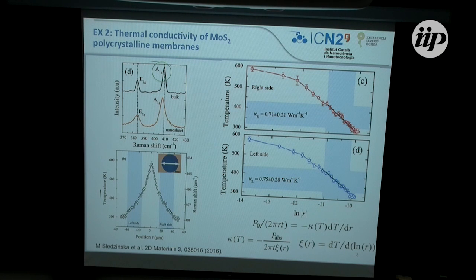So the second example has to do with what our chairman talked on Monday, which is thermal conductivity in molybdenum disulfide. So we obtained polycrystalline molybdenum disulfide, exfoliated and put it on an electron microscope grid, and proceeded with our experiment. Here we use the technique that Joni Ahopelto explained to you on Monday, basically laser Raman thermometry. First of all, we studied the Raman spectrum of polycrystalline molybdenum disulfide. We saw that this is a very good peak to focus on because in the nanosheet it also appears strong, shifted, and we use this one to measure the temperature of the molybdenum disulfide membrane as a function of position.